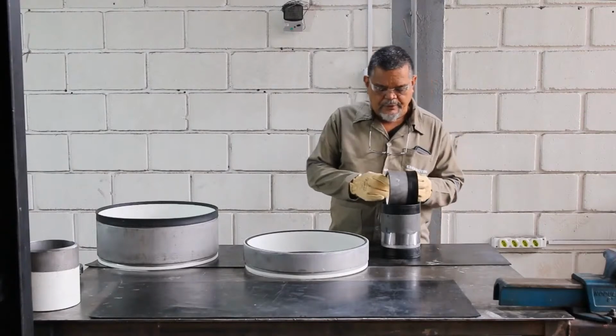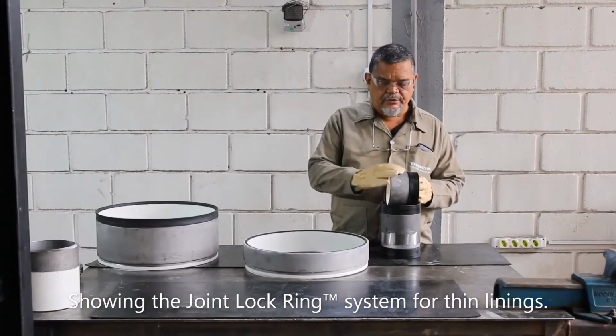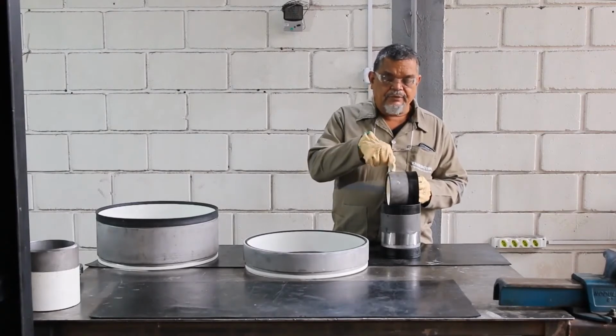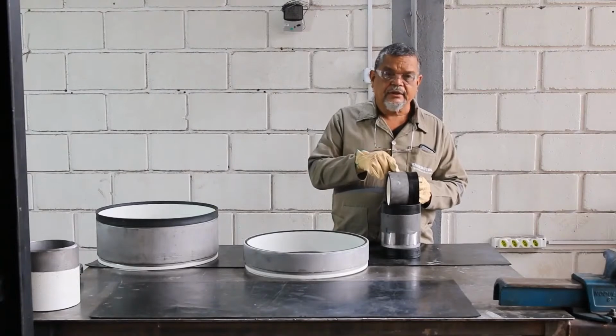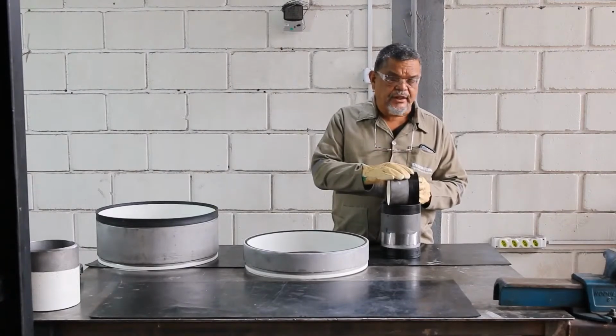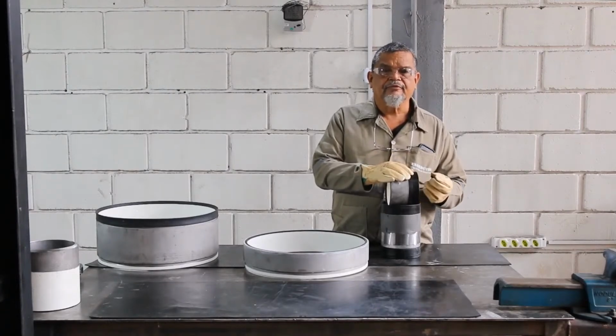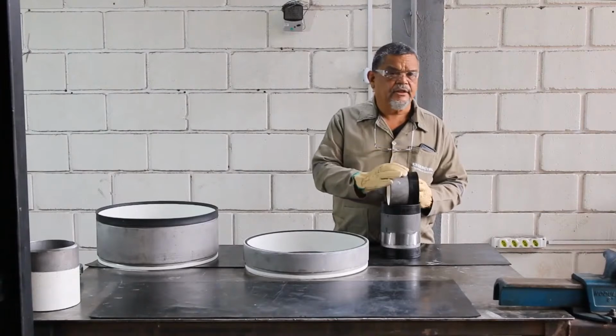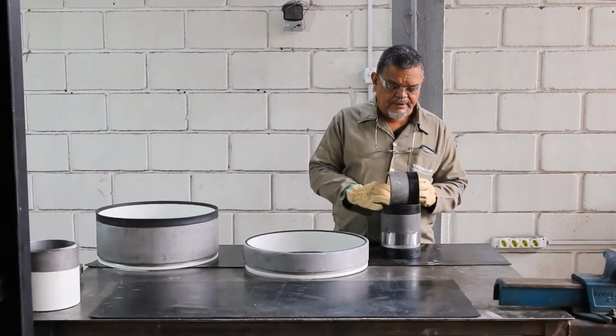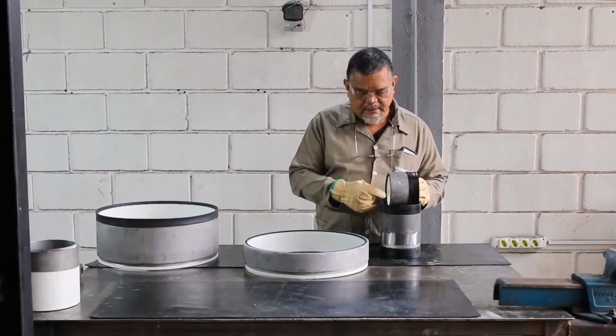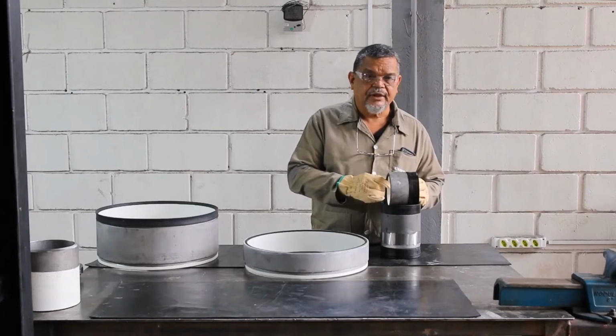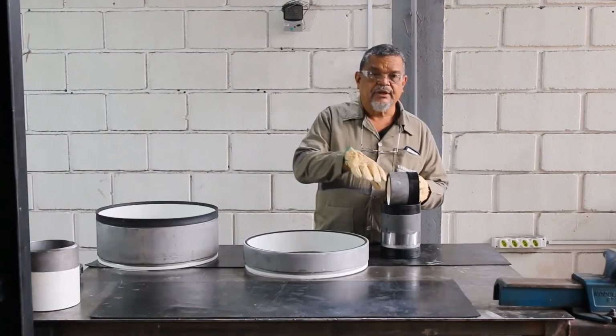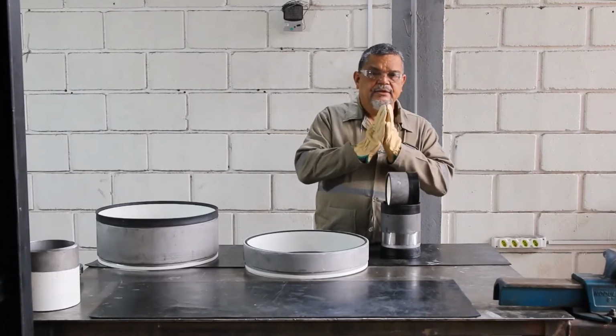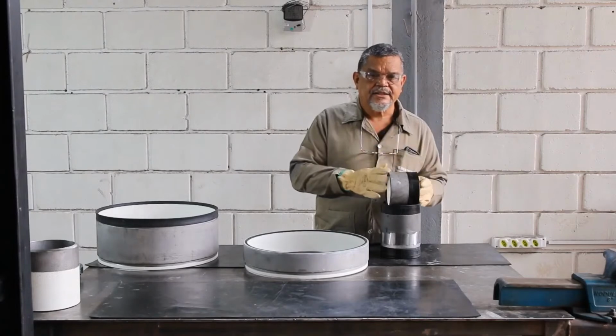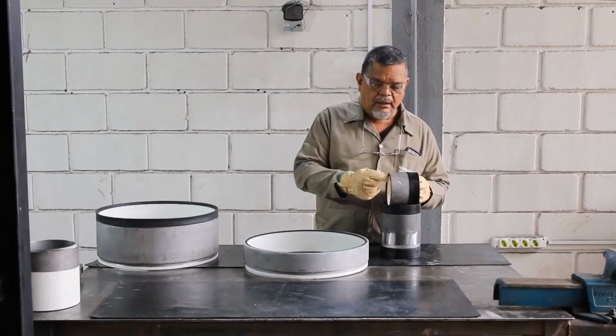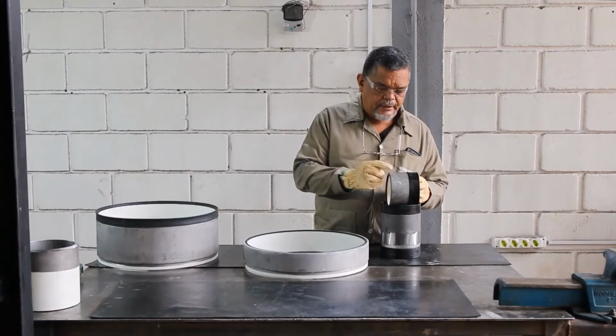We came out with a ring to be inserted into each one of the pipes to be welded. The ring has an integrated insulation layer that is asbestos-free and completely isolated from the flow of the fluid that comes in the pipe. We have a sealing system in the face of the ring where it matches another similar ring to the next pipe to be welded, and these two gaskets compressed against each other effectively seal the possibility of leaking fluid to the weld zone.